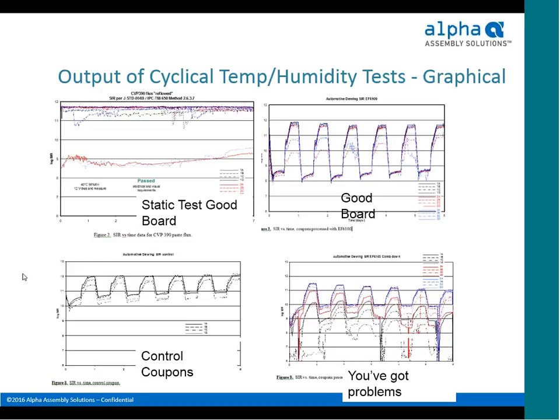On the bottom right, that is not a good result. What you see here is in many instances, the resistance of multiple channels dropping down below what the graph shows and well below the test limits that are specified. In these cases, these would almost act like intermittent shorts on the circuit under those conditions. So clearly not a passing result for that assembly.